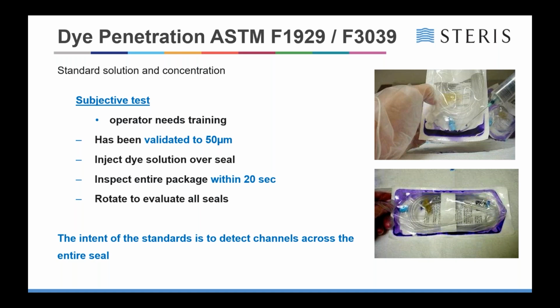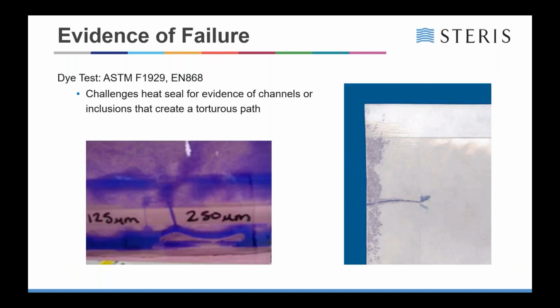The intent of the standard is to detect channels across the entire seal. Sometimes you will get partial channels across the seal. These are not defects, because you still have integrity of the actual pouch or tray retained. A typical example of a defect in a tray is shown here, 125 microns versus 250 microns. You can see that the dye will pour directly out through the defect, and it can disappear within a couple of minutes.